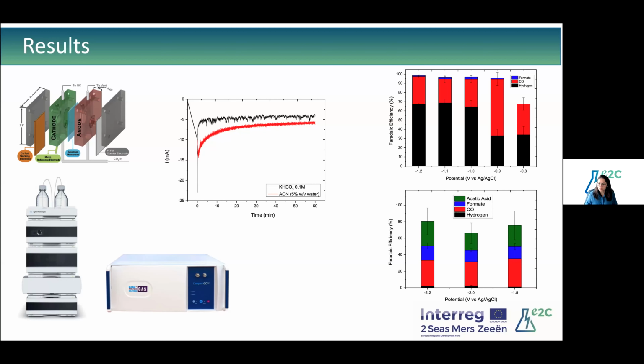You notice that we lost the black bar, which refers to hydrogen. Of course, we had less water in the system, so there were fewer proton donors, and we lost that bar. But we also increased the formation of formate and acetic acid. This kind of result is what we're aiming to obtain progressively, leading to the optimized electrolyte that we're proposing.